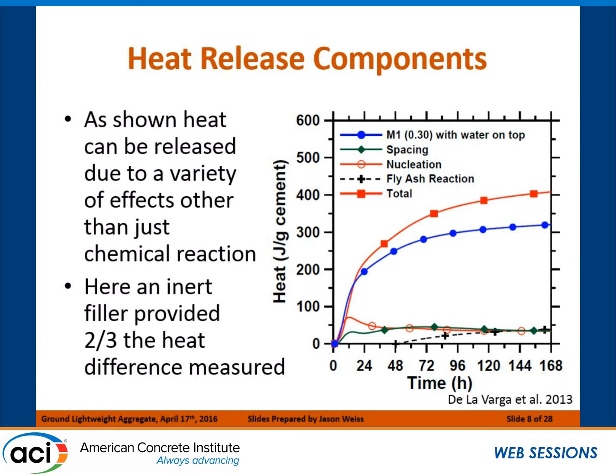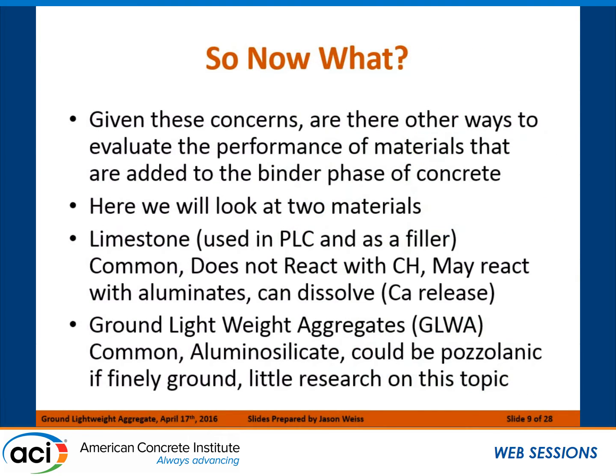So while we saw a massive change in the hydration, only a third of that is really due to the reaction of the fly ash itself, where 2/3 of that is coming from other sources inside of the system. So as we start to look at that, the question was, can we start to look at this and interpret this when we start to look at other types of materials and other types of binders that are going on in the system.